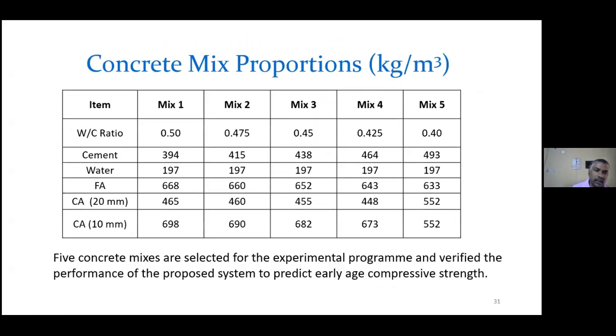Now the mix proportions. Five concrete mixes are selected for this experimental program. By changing the water cement ratio, you get different strength values for the mixes. So five different mixes are selected from published literature, and these five mixes are used for this case study.